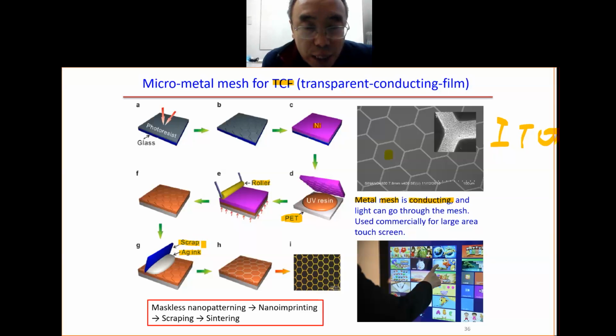This is the same idea as when you install ceramic tile. When you install ceramic tile, you use a similar process to apply the grout. Then you have the silver ink filled into the trenches. Then you do the sintering process. When you do the sintering process, the silver nanoparticles come together to form silver metal. This one is commercialized by the company called SVG.